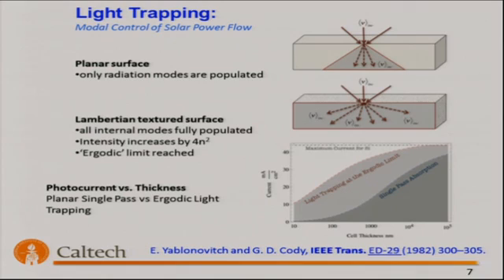And so the first thoughts about how much light could be contained within a solid were actually in the statistical ray optics picture developed by Eli and his collaborators in the early 1980s. This was framed in the ray optic limit and basically suggested that if you had scattering in such a way that all of the internal radiation modes within a bulk solid, in the ray optic limit and in the weak absorption limit, could be populated, then there would be an increase in the intensity, and since the absorption scales with the intensity, of 4n squared.